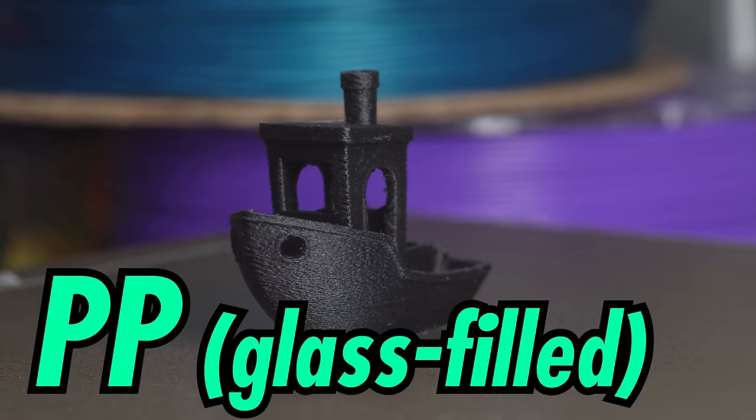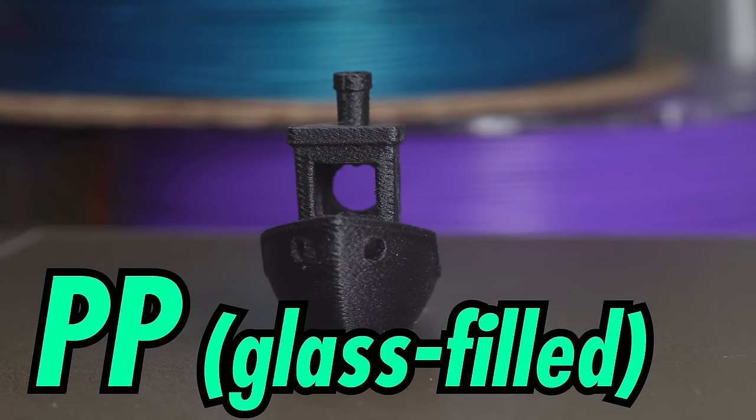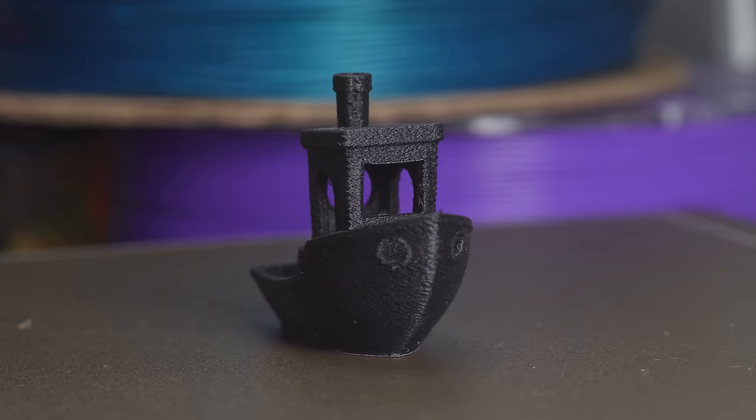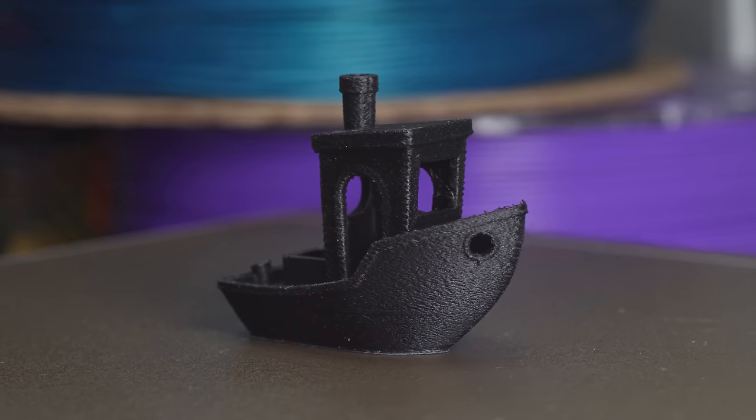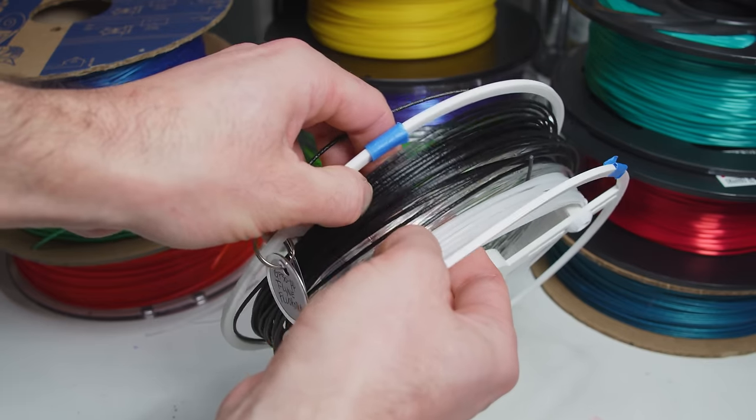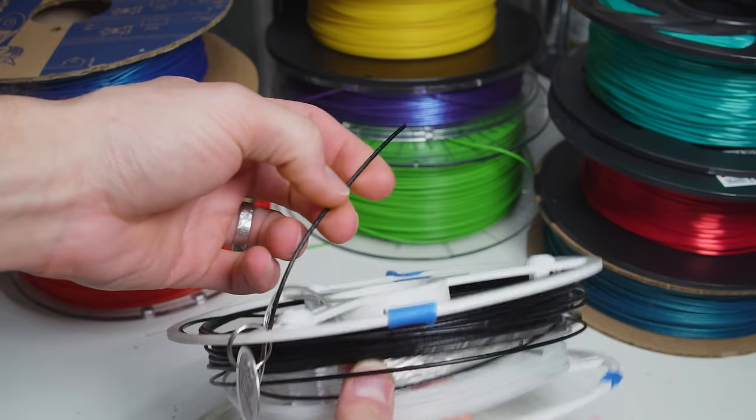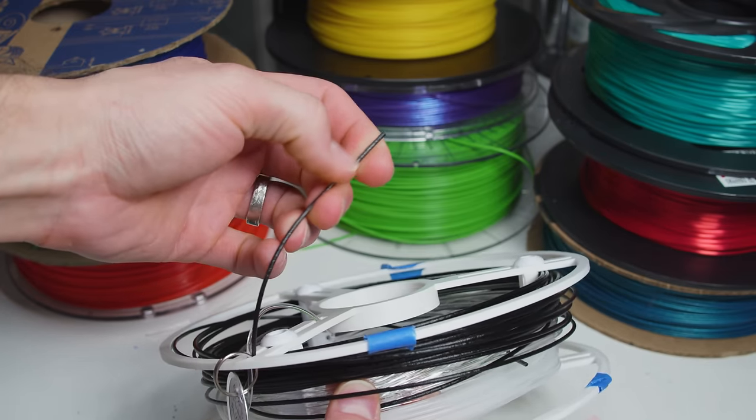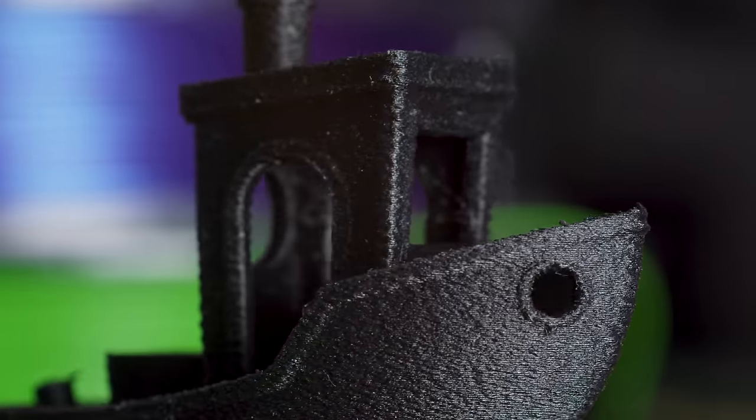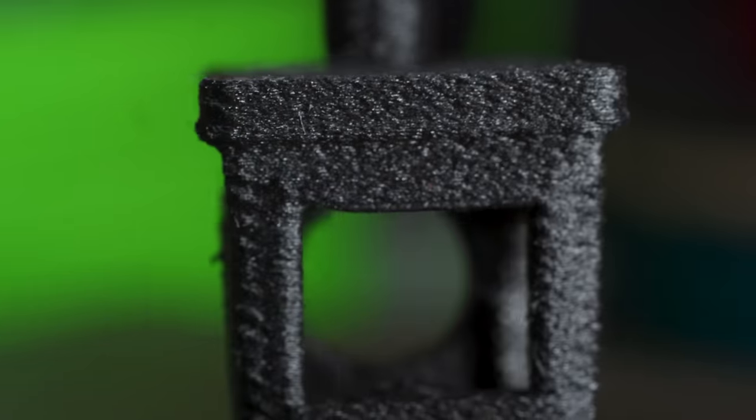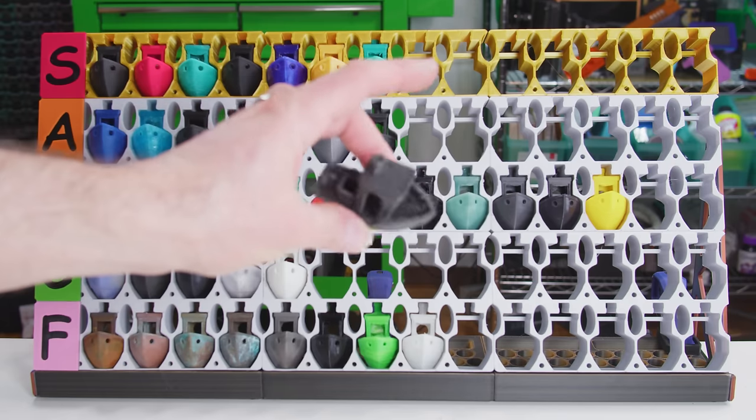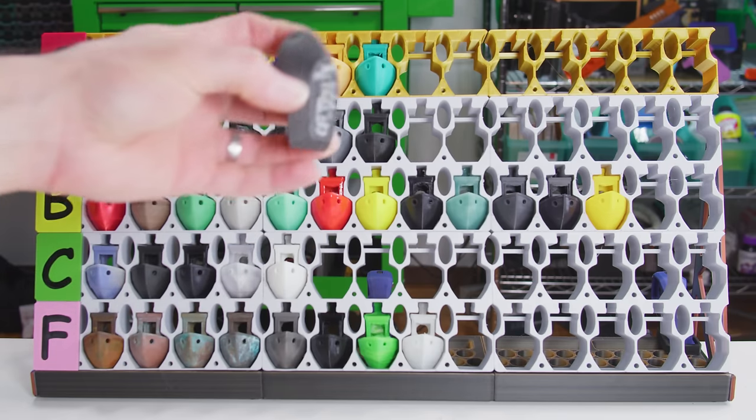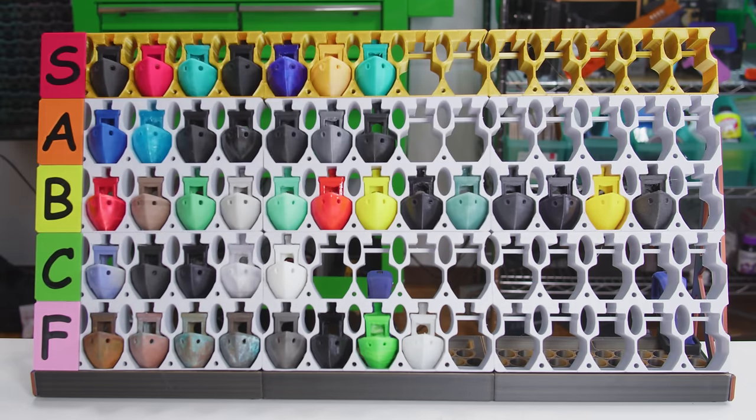That said, Polypropylene composites are fucking spiffy. Glass-filled PP is a standard material for industrial machinery, so unlike other polymers, glass is more common than carbon. This stuff is even more difficult to print than regular. It peels off the bed easier, it curls more aggressively, and demands a direct-drive extruder, hardened nozzle, and an enclosure. But the payoff is bananas. This GFPP is one of the toughest, most durable all-weather filaments you can run on a mid-range printer. It's also unnervingly lightweight, and you get a ton of filament per spool. I'll put GFPP in B-tier. It is unbelievably obnoxious, but also unbelievably tough.